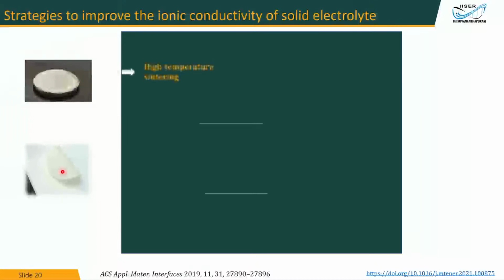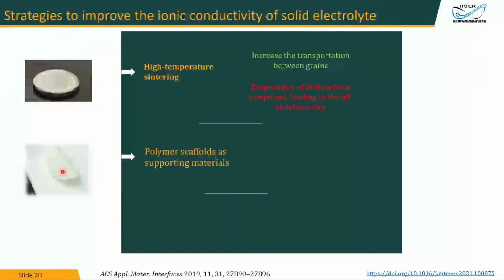So when it comes to solid electrolyte research, we need a very dense solid in order to avoid grain boundaries, so I will have to increase the sintering temperature to a very high temperature, about 1300 and so on. And when I do that, that happens on one side, and I might also want to work on polymer scaffolds, so I can add a little bit of supporting materials. With high temperature sintering, you can increase the transportation between the grains, but what you have to lose for it is the lithium ions that are there in it. So the stoichiometry might be lost when you're going for high temperature sintering. That is a serious problem.